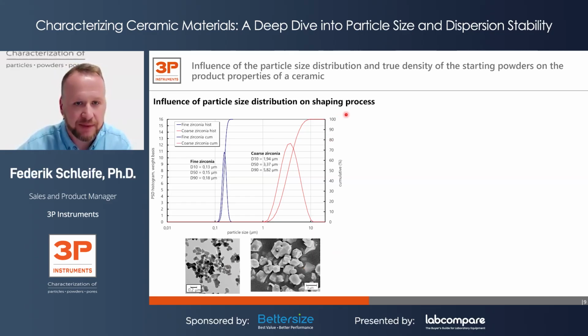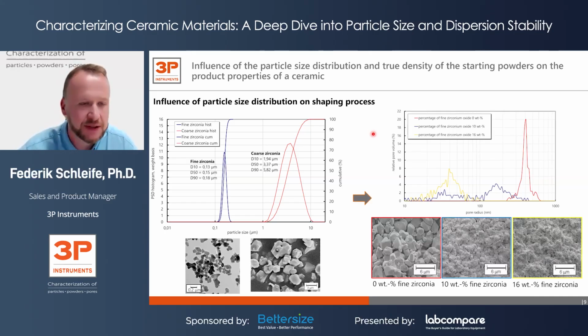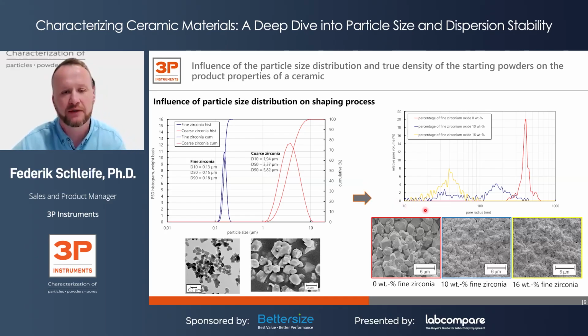So how does it influence the shaping process? With different mixtures of the coarse and fine zirconia, we made some green bodies and investigated their porosity with the help of mercury intrusion. Here you can see the measurement of the pore radius in nanometer and the relative pore volume of different mixtures. The red curve represents the pure coarse zirconia, so with 0 weight percentage of fine zirconia. For the pure coarse zirconia powder, further processed to a green body, you would see a pore radius of around 400 nanometer.